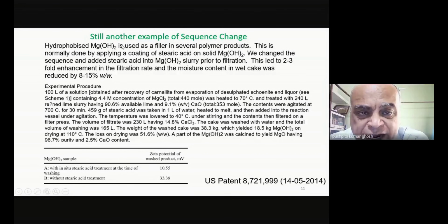What we said is, what happens if we add stearic acid to a magnesium hydroxide slurry before we have done the complete filtration and washing? So we put that in, and it again went and sat on the magnesium hydroxide and made it hydrophobic, and it became very easy after that to filter off the magnesium hydroxide, and we did not have this slimy mass.